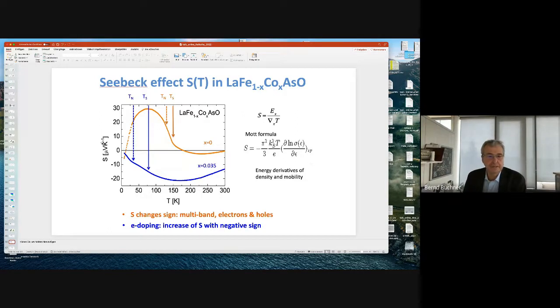And this is now the Seebeck effect without strain, in zero magnetic field. It is close to zero. It even changes sign, and that's due to the fact that the number of holes and the number of electrons are similar, and therefore we have this nearly zero, even this sign change. If you dope electrons, it becomes negative. Okay, that's what we know.